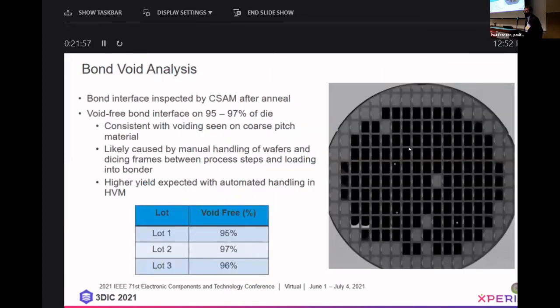This slide shows the acoustic scan, typical acoustic scan of one of our die-to-wafer bonds with this part. And basically, we've been able to achieve in our facility in California over 95% void-free die. And this is similar to the work we've done, a lot more work with coarse pitch material, but it's very similar results. And probably the voids that we're seeing are caused by the manual handling of wafers and die frames that we have to do for loading into the bonder. And we would expect higher yield than this with automated handling in an HVM facility.